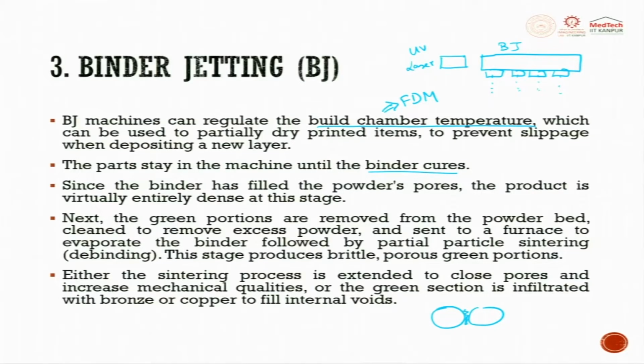It is called green. You can break it when you apply force, but when it goes to sintering, it becomes hard. Next, the green portions are removed from the powder bed, cleaned, excess powder is removed, and they are sent to the furnace to evaporate the binder, followed by partial particle sintering. This stage produces a brittle, porous green portion. Either the sintering process is extended to close the pores and increase the mechanical properties, or the green section is infiltrated with bronze or copper to fill internal voids.